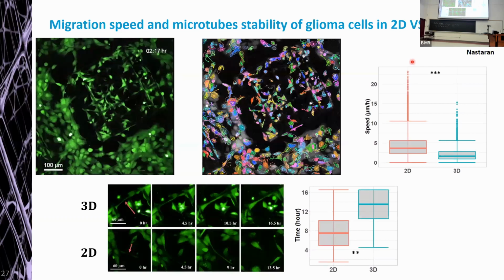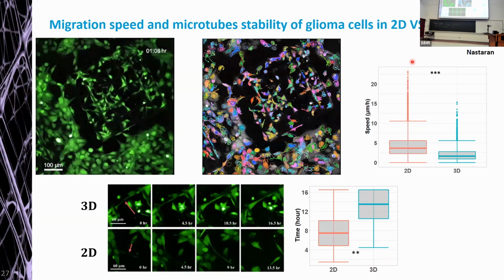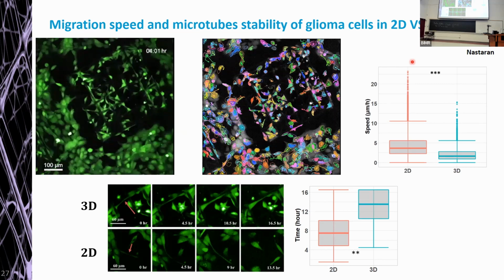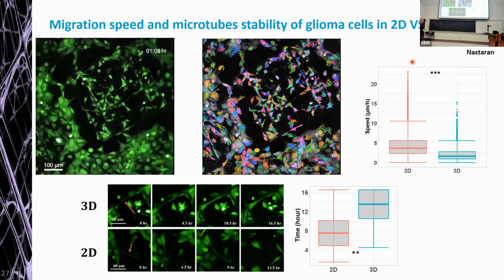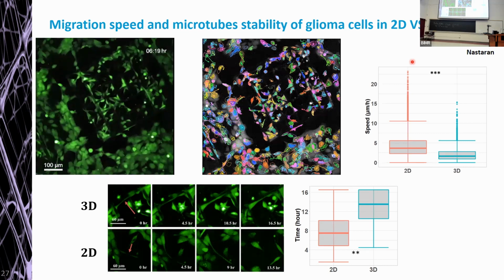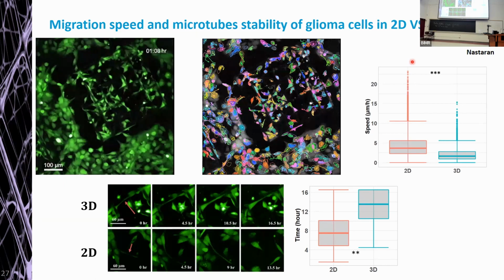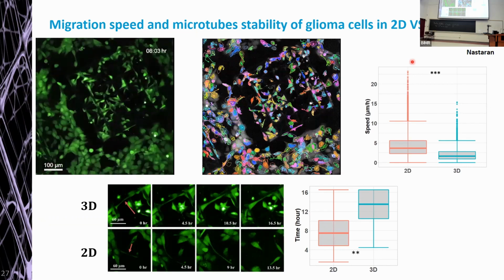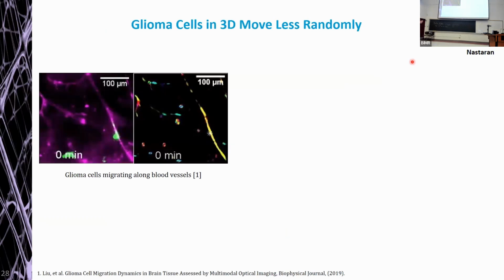We also looked at the stability of our cellular network. For instance, here you can see a tumor microtube in 3D and in 2D. And we observed for how long this tumor microtube was preserved, where here you can see that on average in 3D, the tumor microtubes lasted around 14 hours, or more than. This means one of two things: either the glioblastoma network is more stable in 3D, or the fact that the cells are moving more rapidly in 2D also has an influence on the stability of the network, something that we still have to investigate further. And then the last thing that I want to show you related to this work is